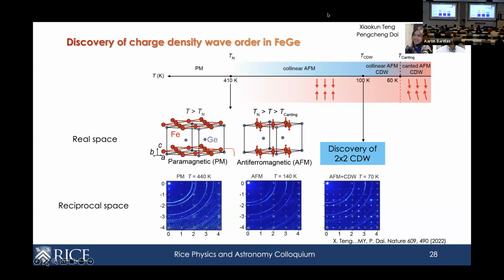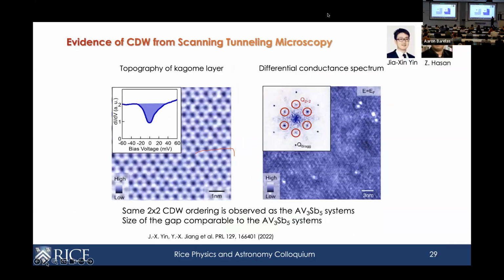This is not expected because there are very few examples of materials where you can have a CDW order that appears well within the magnetic order phase. This is very rare. So then we went through a lot of collaborators to check for this CDW order by different probes. This is one of the first ones. We collaborated with a Princeton group to look at real space. Can they actually confirm there's a real space charge density wave? They can. This is the STM, scanning tunneling microscopy image. And when they take the Fourier transform of this, they can see the 2x2 peaks appearing. So there is indeed a charge density wave order from STM.